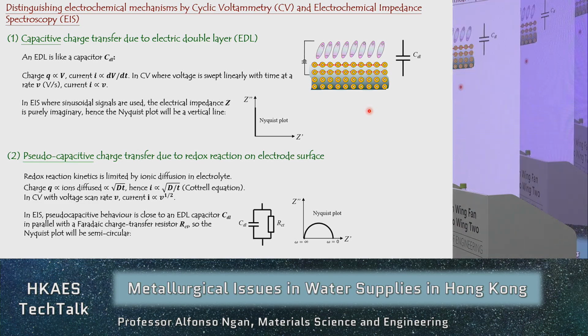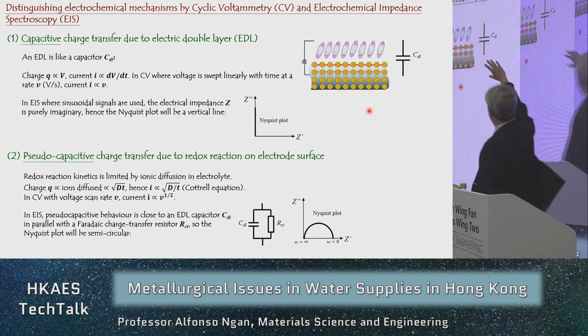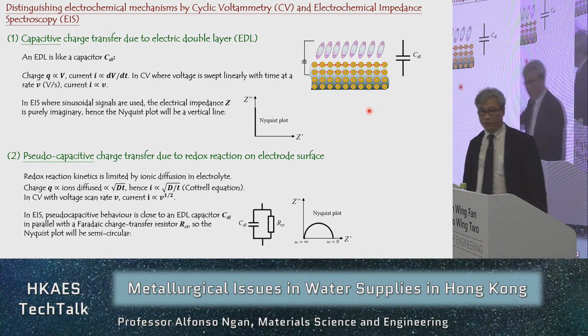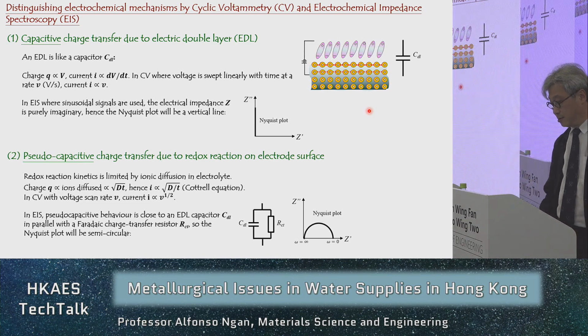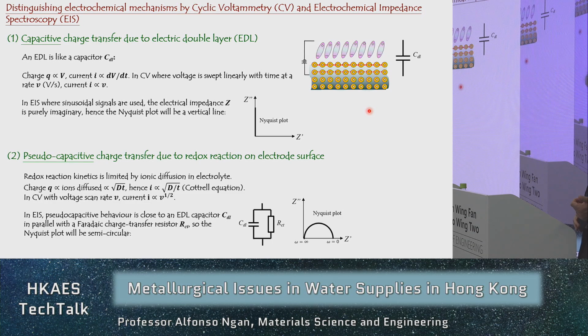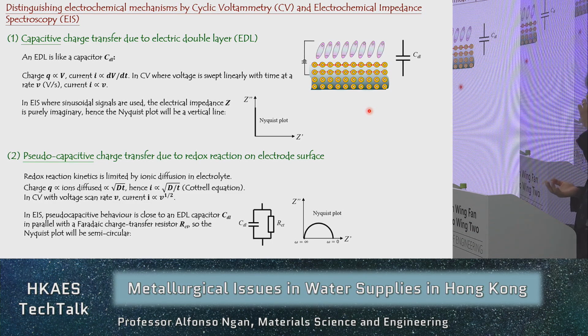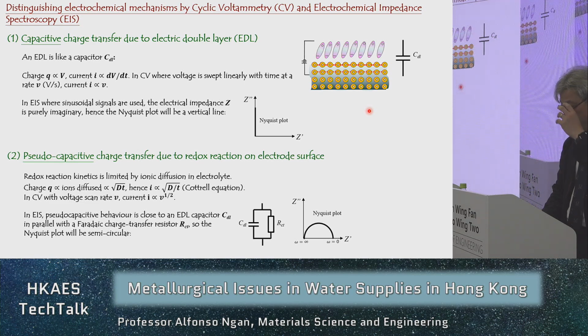Now, if you oscillate the voltage between the electrolyte and the metal, and then you do what people call an electrical impedance measurement, the voltage and the current are now AC, not DC. Okay, so when you oscillate the voltage, the current will also oscillate. So there is an impedance between the two, and there may be a phase lag between the two as well. So the impedance is actually an imaginary number, going back to our basics.